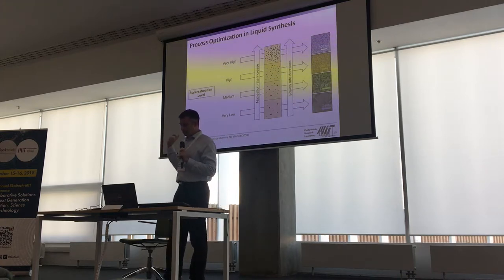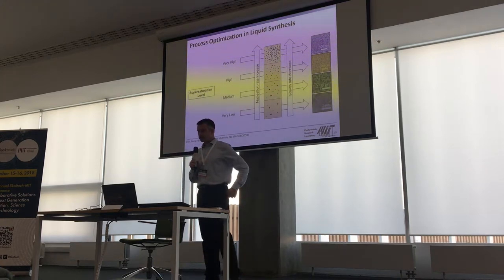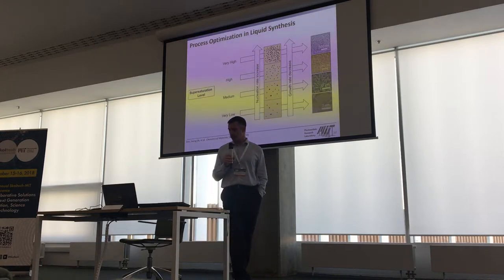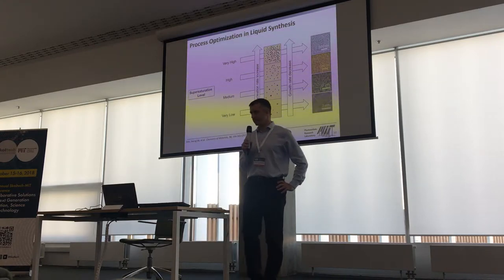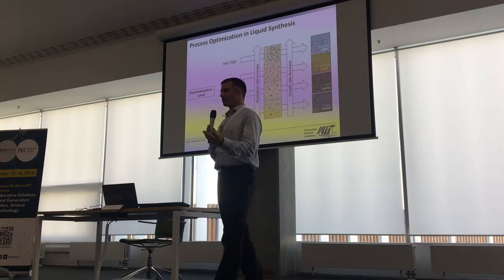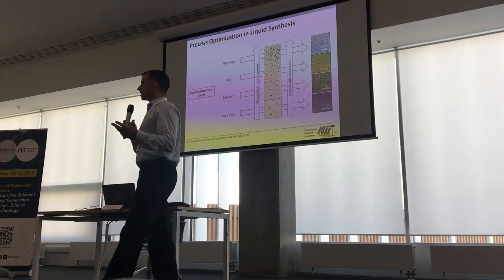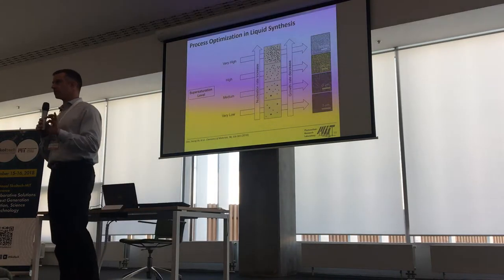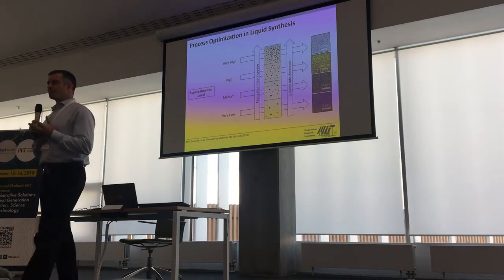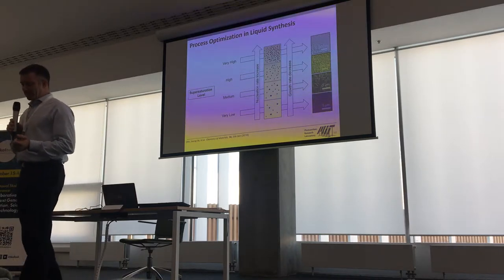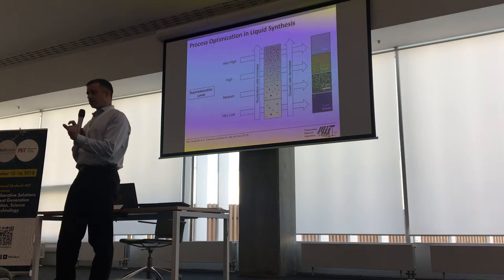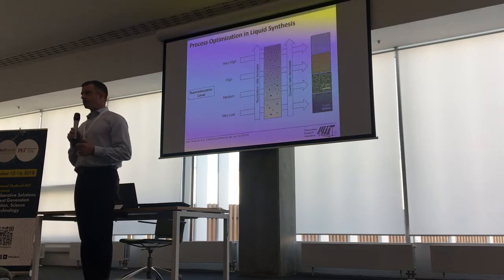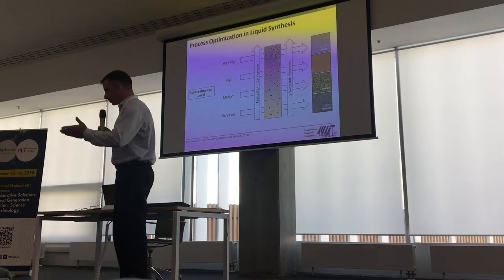So this is just a screenshot from a study on the creation of bismuth-based precursors for solution synthesis. This was a big challenge because bismuth doesn't dissolve readily in water. Its solubility, I think, is on the order of 10 to the minus 9 grams per liter. So it really doesn't dissolve well into water. If you combine bismuth with the right type of solvent, though, you can get very high concentrations dissolved in liquid form, which you can then use in your growth.